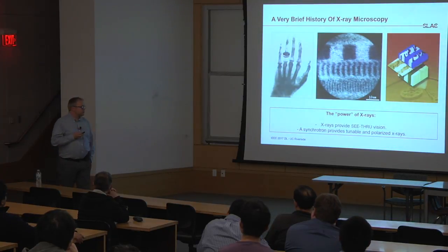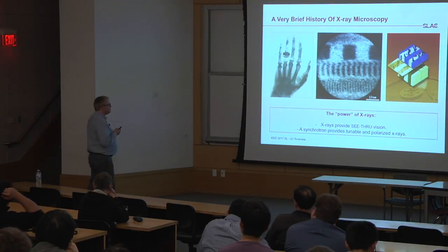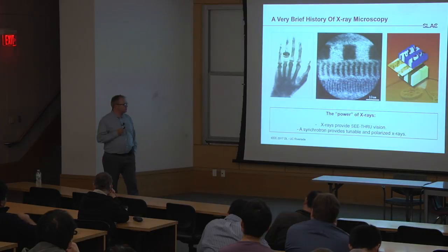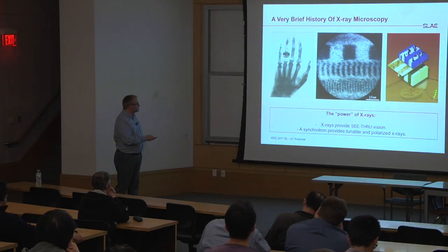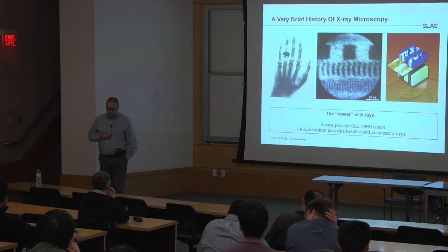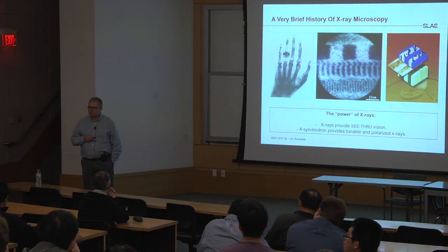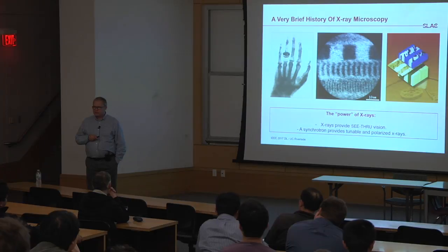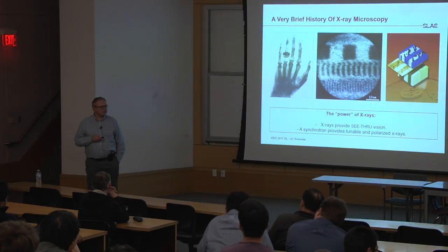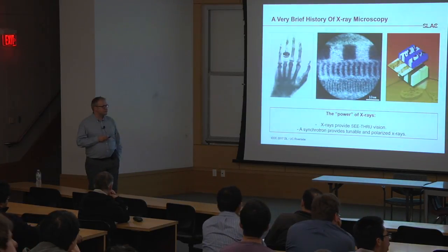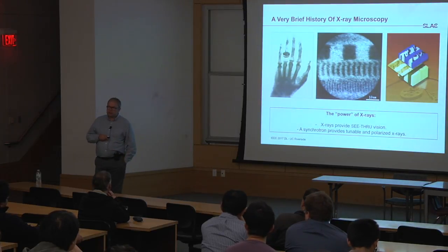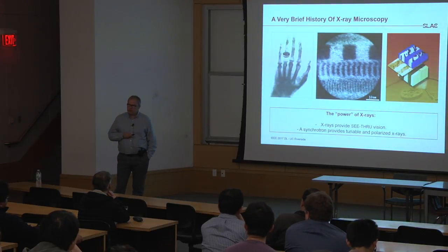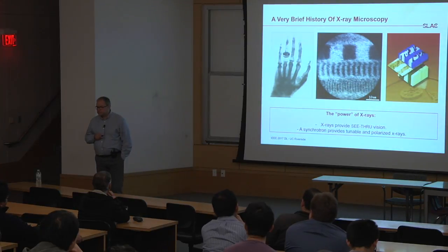The spatial resolution in spectroscopy depends a little bit. Right now, I would say in the PEEM microscope, these images were taken at probably 100 nanometers, roughly. In the STXM we are currently using, in our microscope, it's not as good. It's about 200 nanometers. In other microscopes, it's probably 50.